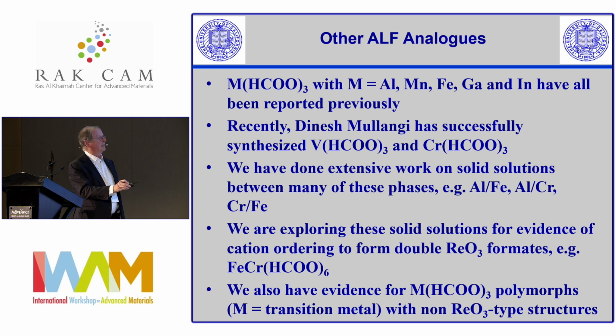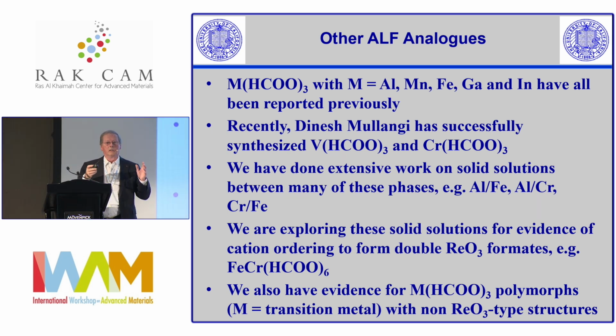We've also been looking at these solid solutions for evidence of cation ordering to form double ReO3 formates, such as this one here, the iron chromium. What we initially thought were solid solutions, and not all were solid solutions, you get ordering in the center. This is most unusual because we're getting ordering of two cations which are quite similar in size and with the same charge. But we have a single crystal structure of this, so there's no doubt about it. We've also got evidence for other formate polymorphs with transition metals that don't have rhenium trioxide structures.